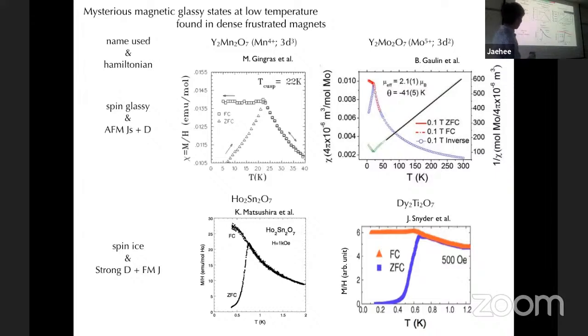On the other hand, the holmium and dysprosium samples are called spin ices. They have a strong single-ion anisotropy, and then a weaker ferromagnetic exchange. But you can see here, they all show this hallmark of glassy behavior, zero-field-cooled and field-cooled hysteresis here. Another system, in fact, this one has this anisotropy term.